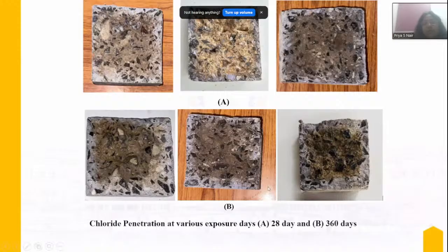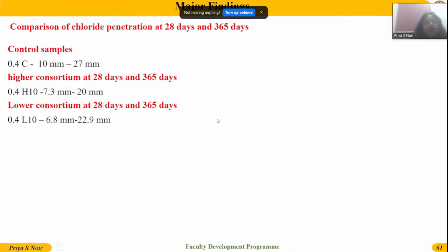We can see this is the 28 days sample, and then this is 360 days. The 360 day samples do not show much. The white precipitation is the depth of penetration, so we take the average depth of penetration. The control sample shows a maximum of 27 mm at 360 days. The higher consortium shows a maximum of 20 mm, and the lower consortium 22.9 mm.